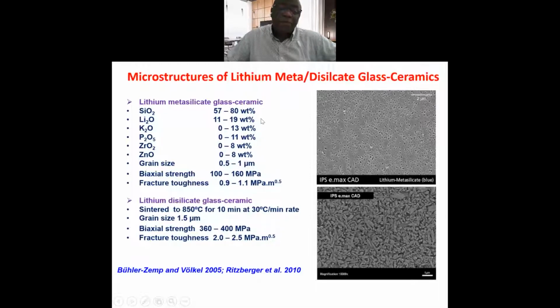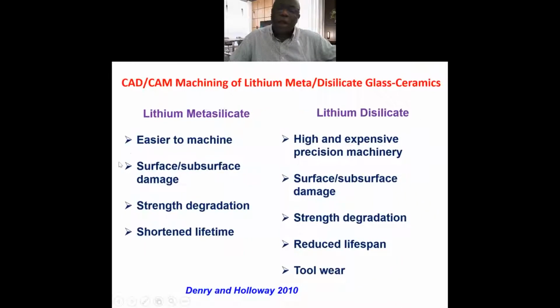When this material is now sintered to 850 degrees centigrade for 10 minutes at this heating and cooling rate, the grain size will improve, and also the biaxial strength and the fracture toughness of the material will improve. So the dental restoration can be processed using the tool. There you can see the pros and